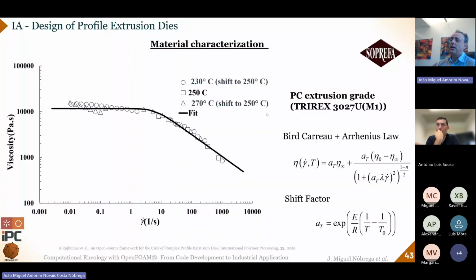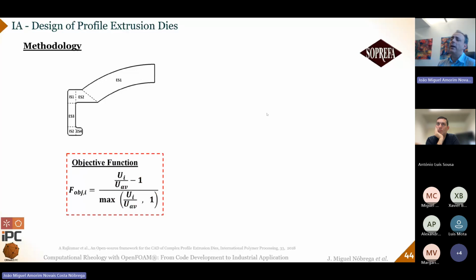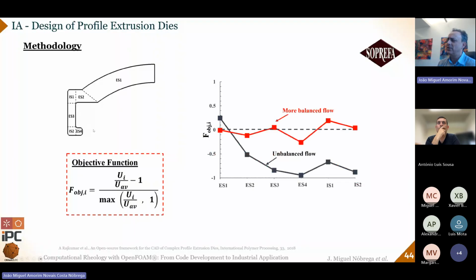In this case, we had to fit the behavior of the material to have an actual constitutive model used in the code. And in order to balance the flow, we divide the cross-section into different elemental sections, and then we quantify the flow distribution through an objective function. The purpose is to have all terms of the objective function equal to 0. This is not possible in a real profile, so we want to get as close as possible. And if the terms are far away from 0, it means the flow is expected to be unbalanced.